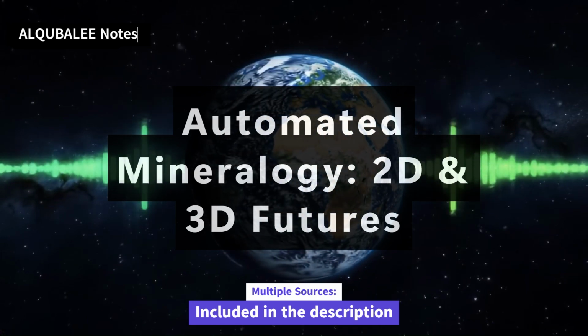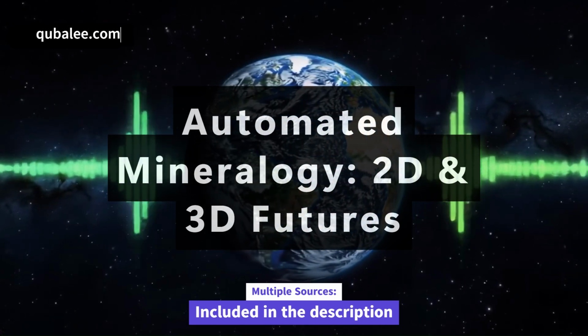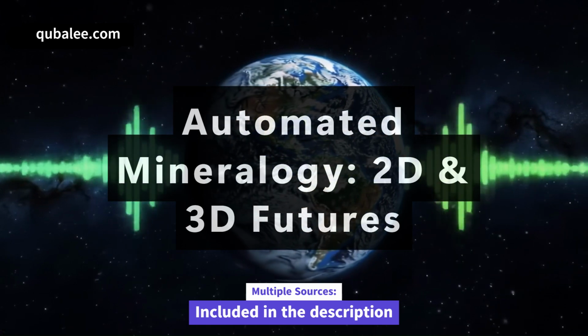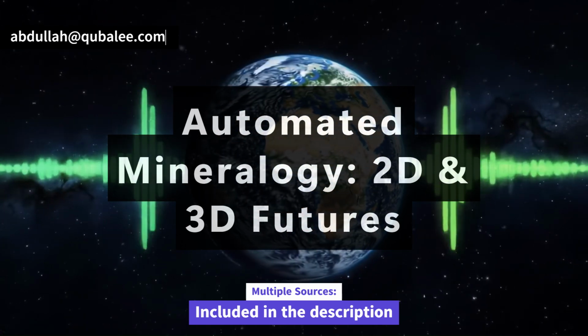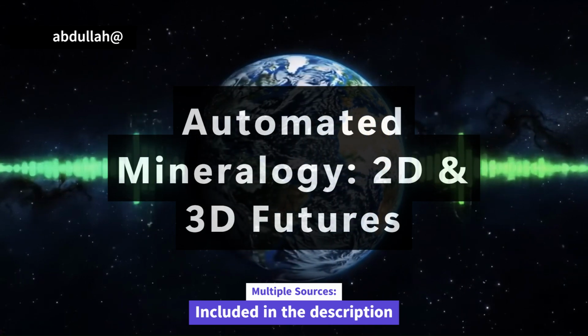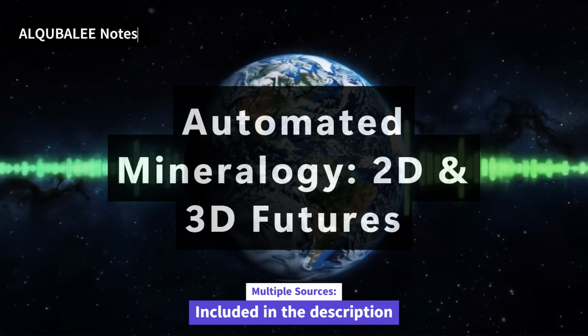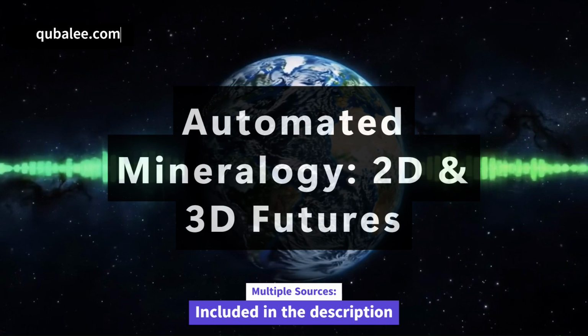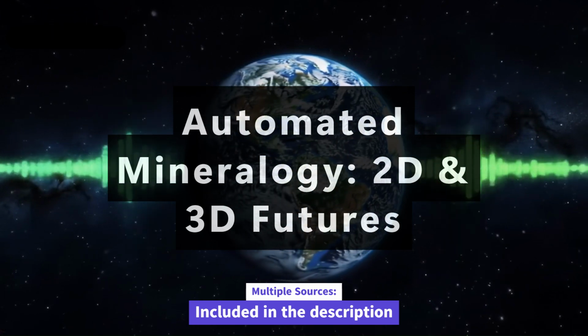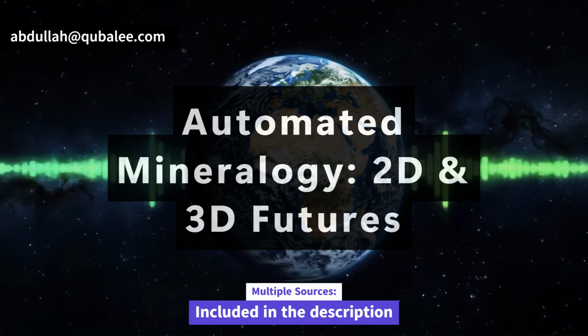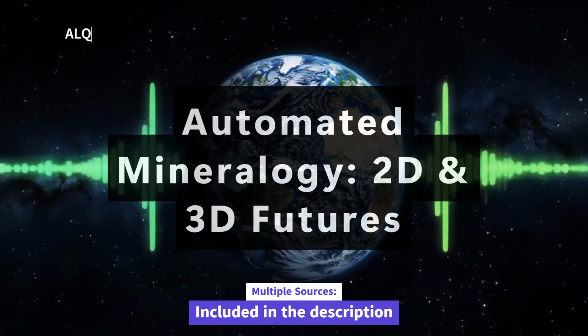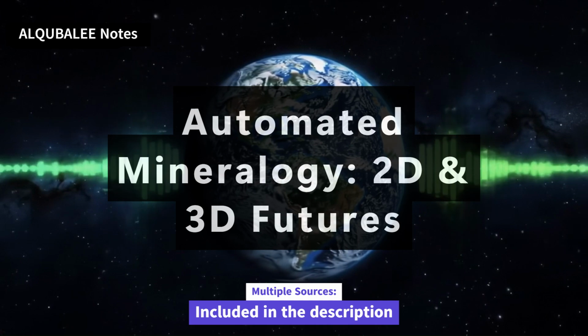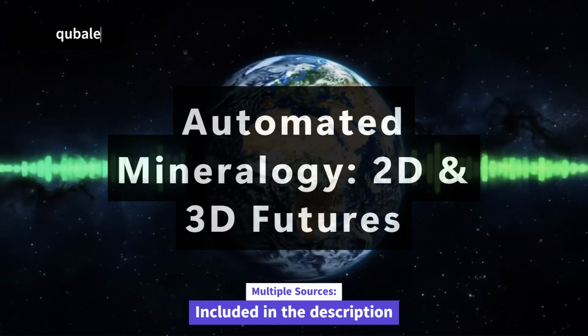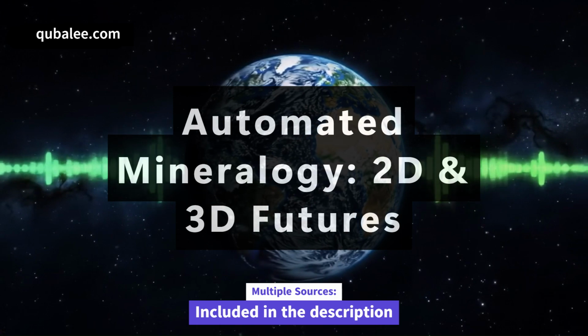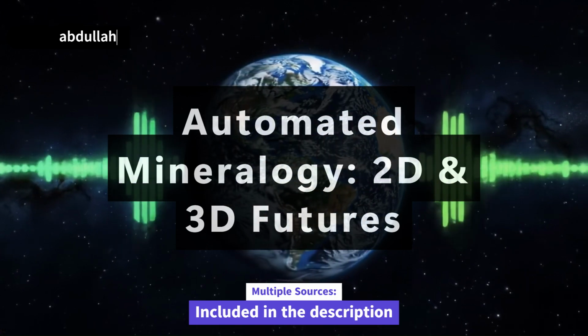Yeah. But how does it actually do it? Let's get into the nuts and bolts based on these papers. Okay, the basics. It usually starts like traditional SEM-EDS. You've got a focused electron beam hitting the sample surface. And that interaction, that electron beam hitting the material, makes the sample give off X-rays. And that's where the EDS detector jumps in? Precisely. The EDS detector measures the energy of those X-rays and also how many X-rays of each energy come off. It does this at lots and lots of tiny points, pixels, across the sample surface. So you end up with an X-ray fingerprint, a spectrum, for every single pixel. Exactly. A unique X-ray spectrum for each little spot.